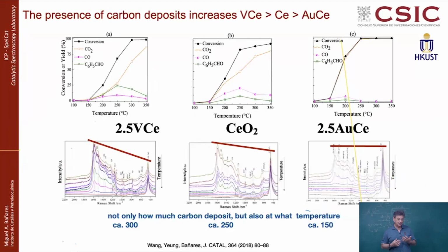And we were assessing the performance of this material for toluene combustion. Toluene is a representative volatile organic component for indoor air quality. So basically you are burning around 1000 ppm, because indoor air quality usually you are dealing with ppm concentrations of contaminants. The Raman and the operando Raman study shows you on the top part you have the activity. This is the bare ceria. It's converting CO2 quite okay.